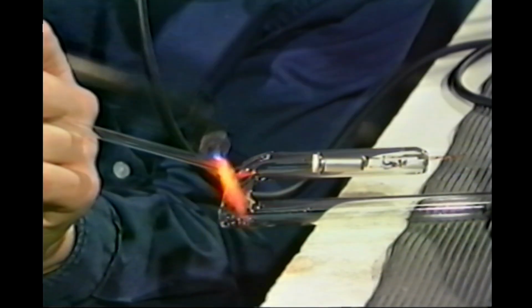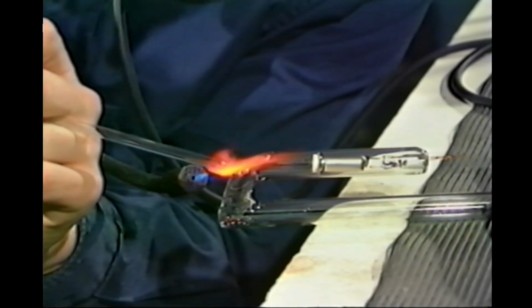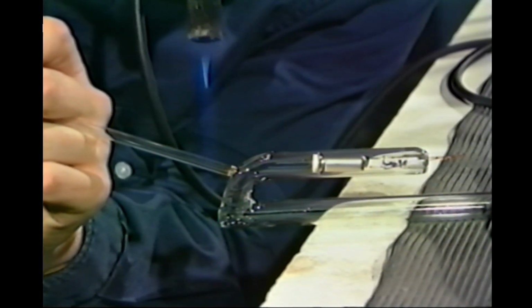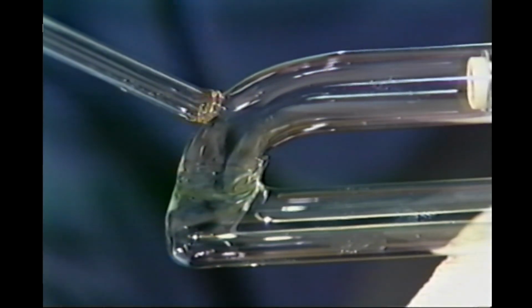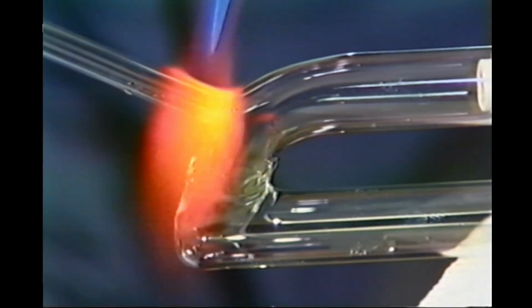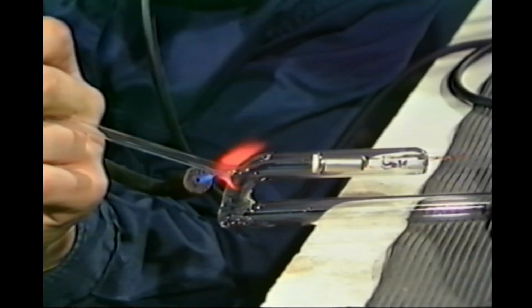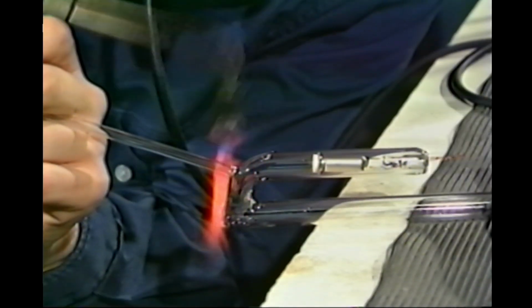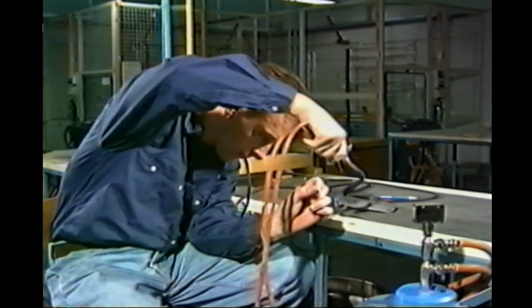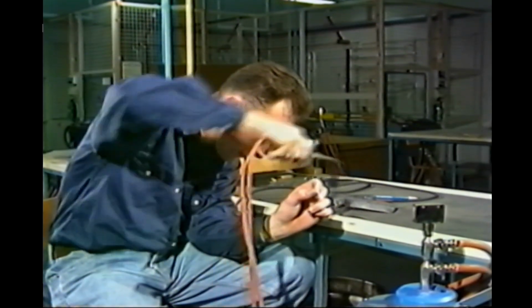When both parts melt to a dull red heat, remove the flame. Touch the stem to the hole, blow slightly and pull back slightly. Now, melt the stem glass just behind the joint line, making sure there is no push or pull motion by the hand holding the stem.